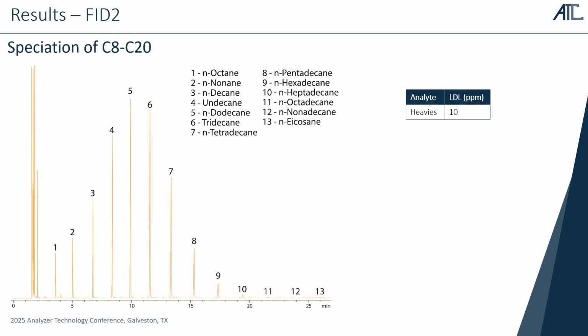Then we just have to wait for those ovens to cool back down so that we can start the next injection. So with every injection, every 35 minutes or so, we're able to send off data giving all of these analytes' information to the process. The FID LDLs are sitting at about 10 ppm on each FID.